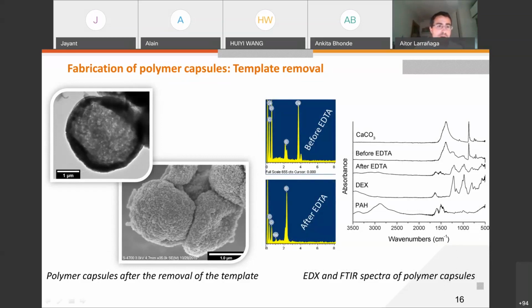This was further confirmed by TEM observations, where you can also see that the sacrificial template was removed from our polymer capsules. But to be completely sure that we completely removed our sacrificial template from our polymer capsules, we performed some EDX and FTIR spectra, where we found that after the EDTA treatment, those peaks and those signals corresponding to calcium carbonate were completely removed, suggesting that the sacrificial template was completely removed from our polymer capsules.